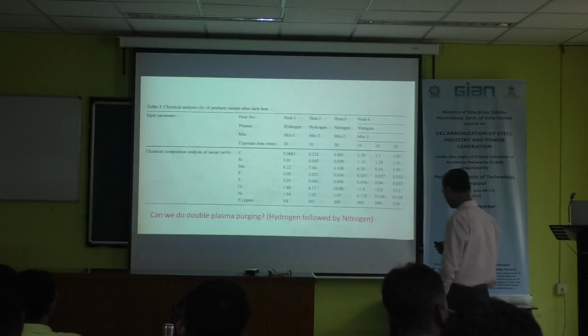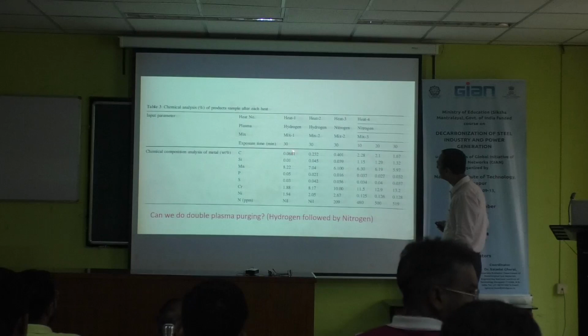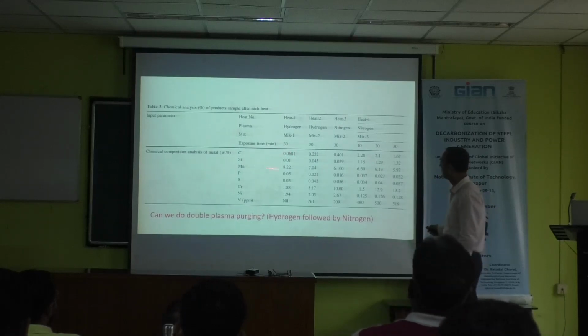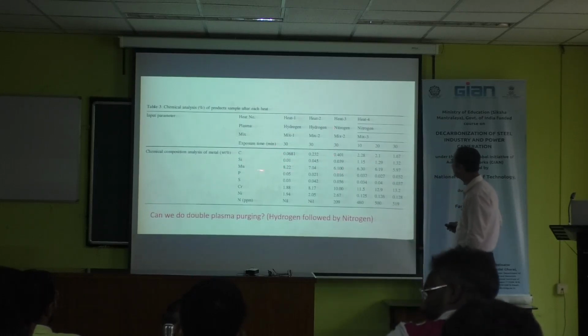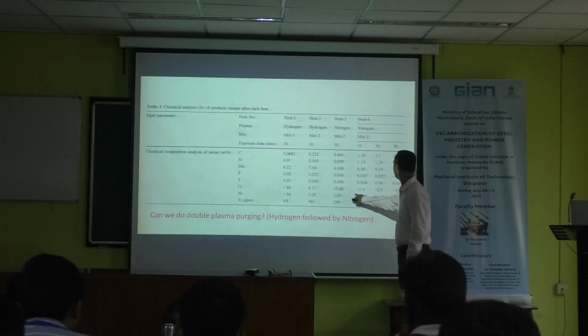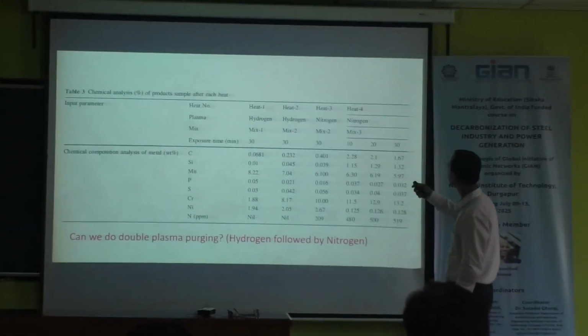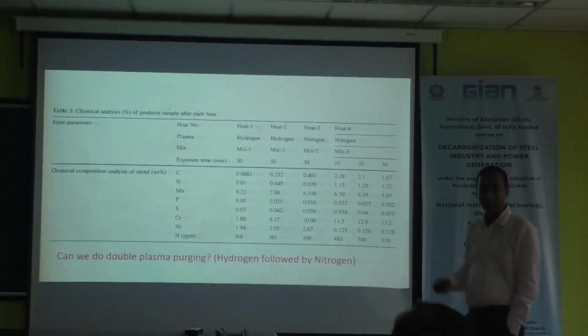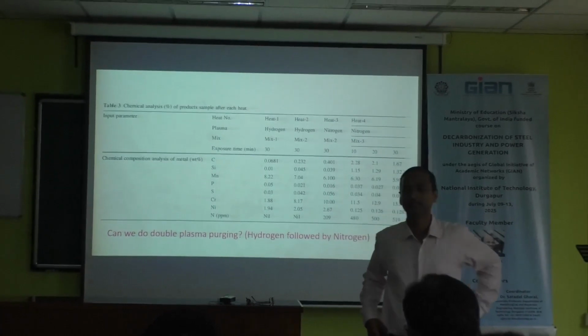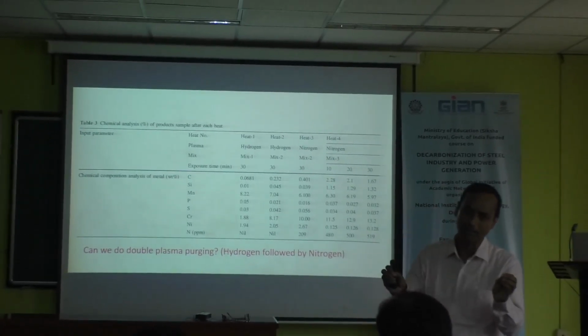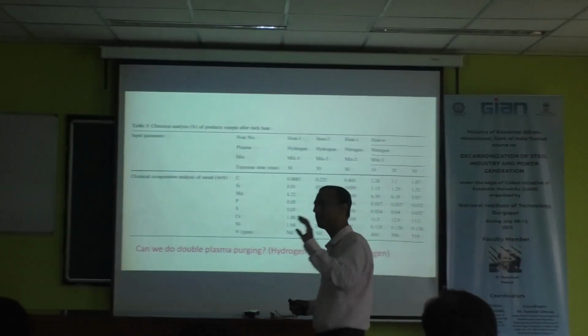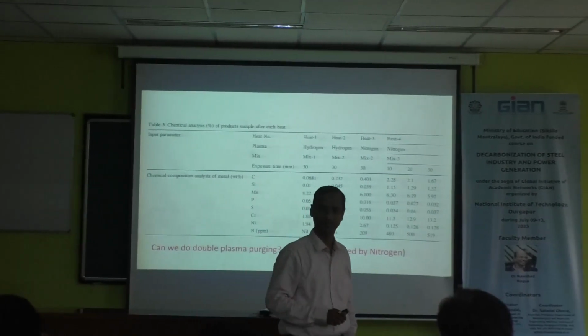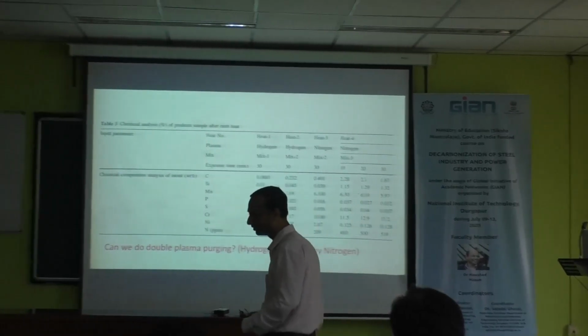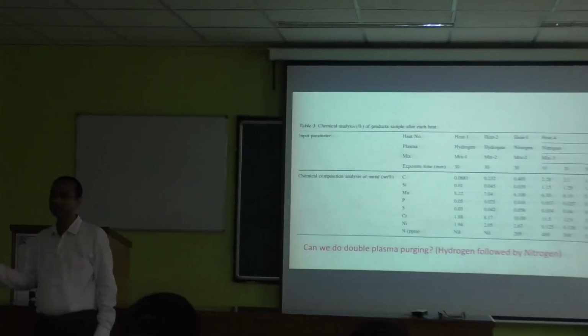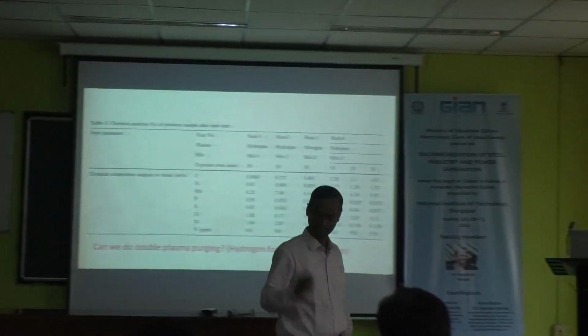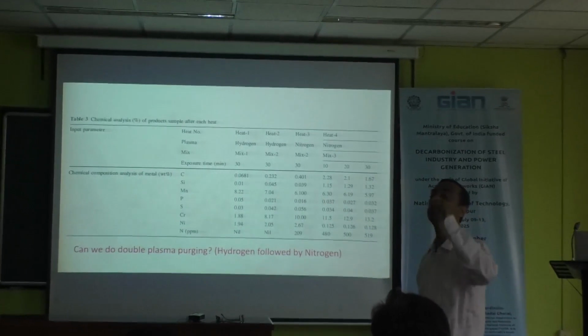Then the beauty is, here you can see when you use hydrogen, carbon is less. But when you use nitrogen, you can see the chromium content here, in mix number 3 with nitrogen. And our requirement is also the nitrogen. Therefore, if you change the composition of the plasma, what will happen? When your requirement is nitrogen absorption, you put in nitrogen plasma. Then you withdraw the nitrogen plasma and insert the hydrogen plasma. What will happen? Hydrogen will react with the carbon, as I have discussed in the past case.